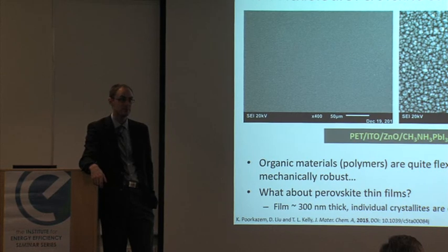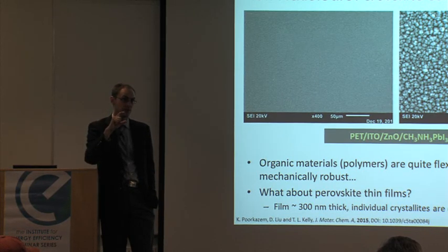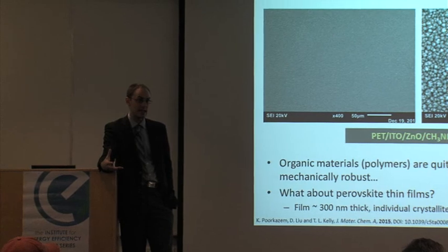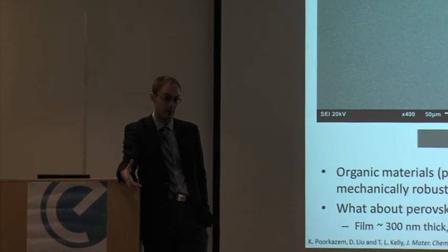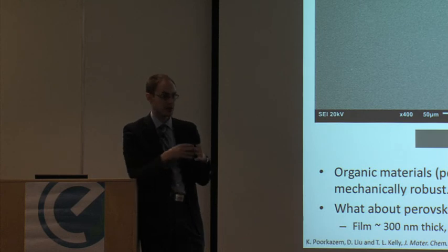Yeah, so in using the zinc oxide nanoparticles instead of a mesoporous material, there's a huge difference in surface area between those two. Is that going to have a really significant effect on the efficiency of your material? Potentially. So it comes down to the crystallinity and the quality of the film that you put on top of it. In the case of the mesoscopic device, you don't necessarily need a long charge carrier diffusion length because it can be sucked up by the TiO2 extraction layer. In our case, we do because the perovskite is carrying those charges in both directions.